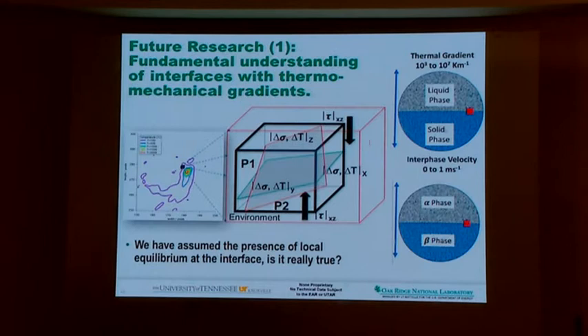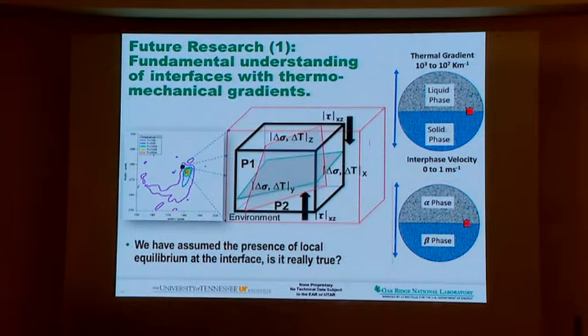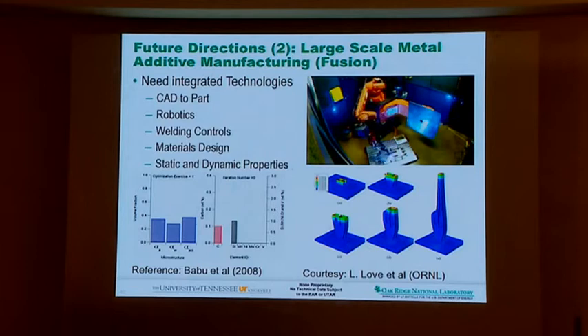As a metallurgist, I want to understand a little bit further because all the theories which I showed you, the data was collected under zero thermal gradient. That means in isothermal conditions. Is it valid, those properties for this huge variation of thermal gradient? We don't know that. So we need to understand the interfaces between liquid and solid, solid and solid. That you need to do a very detailed analysis using experiment and also in-situ measurements in synchrotron. That is ongoing, so we need to focus on that. The next thing is from the application point of view, because it's similar to welding, now you can actually use a robot and welding and make a large-scale structure.